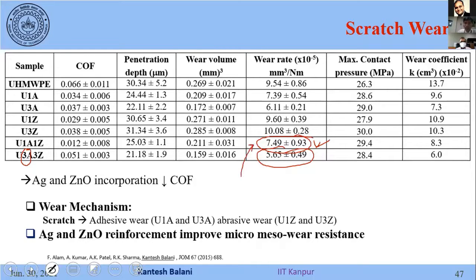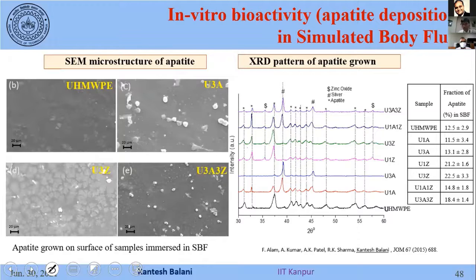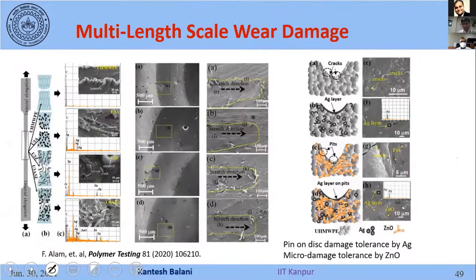So we basically recommend that we should go for 1A 1Z because of its optimal response, either in terms of cell attachment, antibacterial efficacy, wear and tribological response. And we have also done bioactivity testing, and what we see is that zinc oxide is much better. It gives rise to much higher apatite deposition on the surface. And again, we have done tensile testing of various materials, and it also tells us how we can get a synergistic effect by adding silver as well as zinc oxide. So this is the summary.